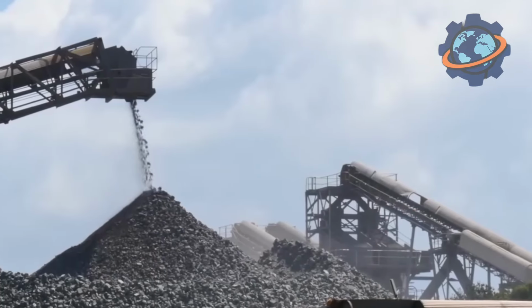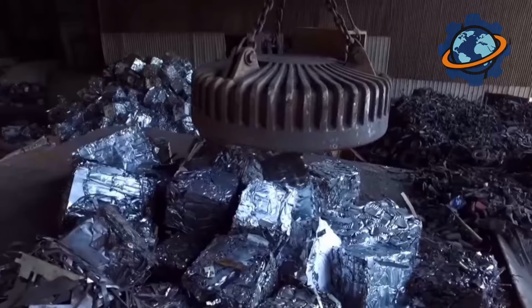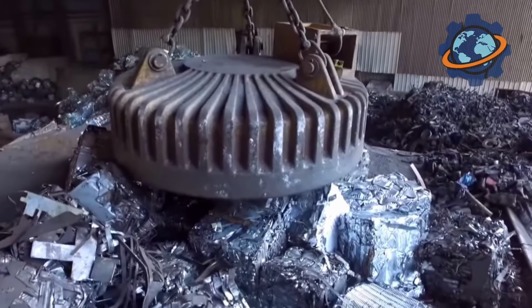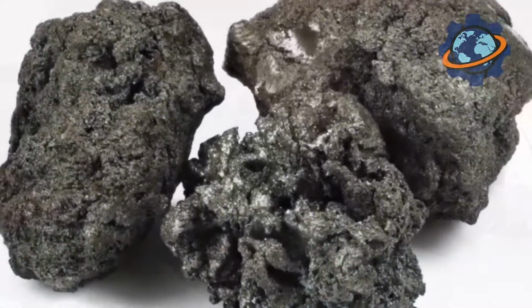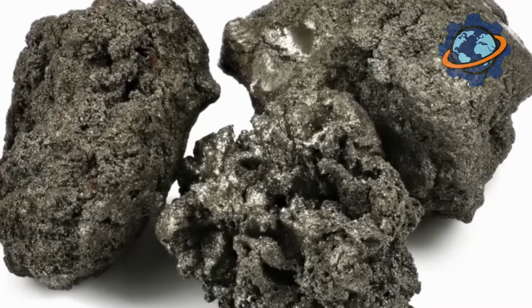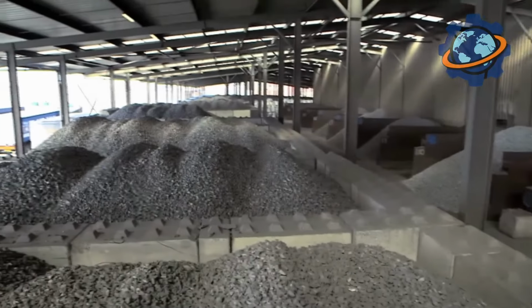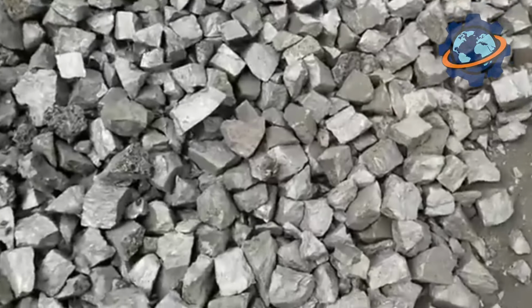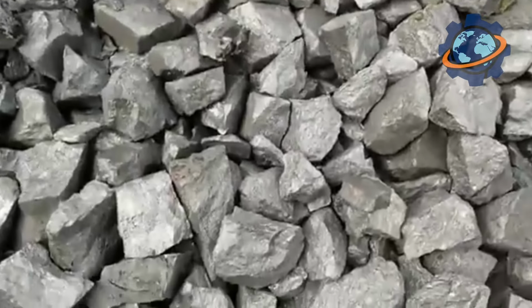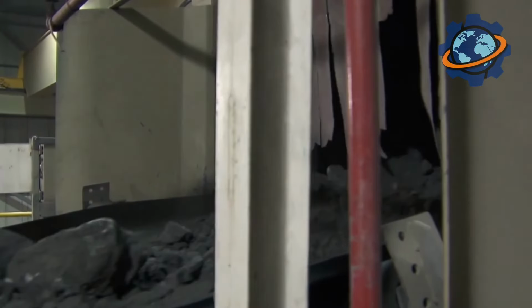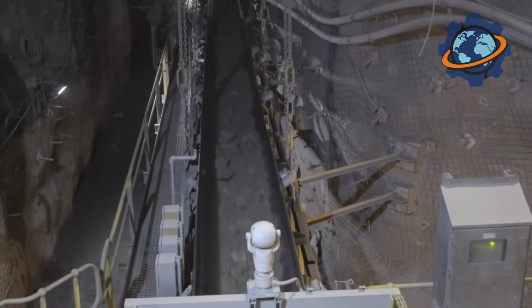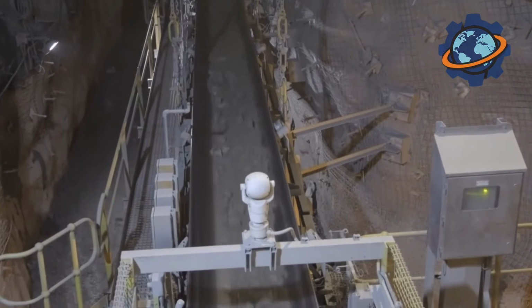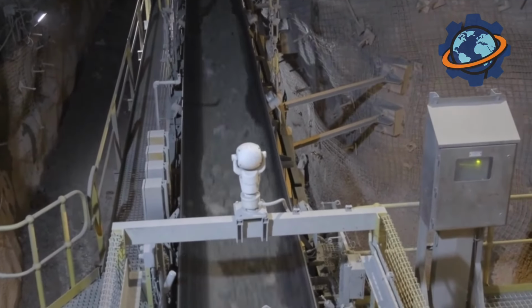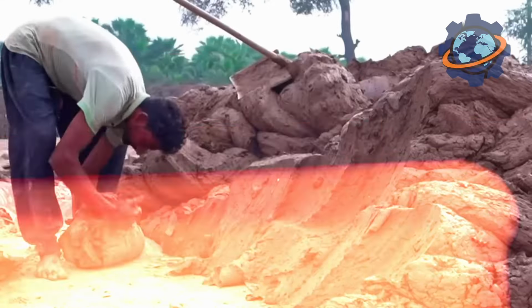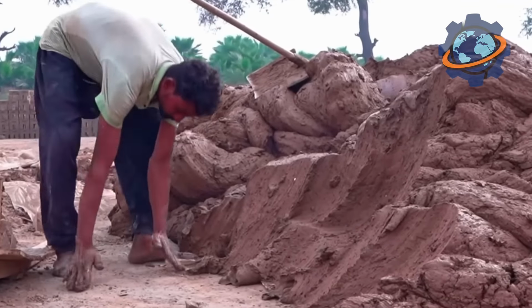So, the process begins with the preparation of components. The mined clay and other rocks, as well as the pre-prepared chamotte, are sent to the crushing line. Giant crusher jaws break large pieces, and then roller and ball mills relentlessly grind them into a fine powder with a clearly defined grain size. Control of the fractional composition is extremely important because the future density, and consequently, the strength and thermal conductivity of the brick depend on how tightly particles of different sizes can pack together.